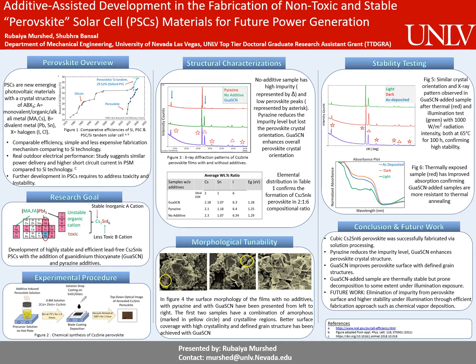Figure 4 represents the morphological tunability of the perovskite surface, where the amorphous regions present in the no additive and pyrazine samples are marked in yellow circle. The guanidinium thiocyanate sample in the most right shows defined grain structure with improved crystallinity, which is very important for the charge extraction capability of the perovskite. Following the favorable results achieved with guanidinium thiocyanate, we have continued our next step with this additive.